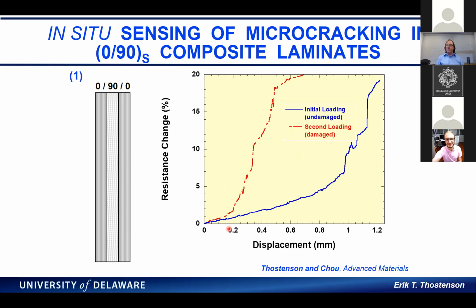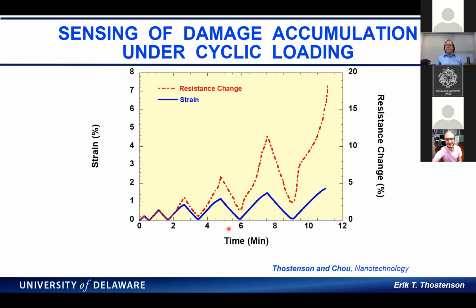So this was encouraging. So we did some more work where we were looking at if we loaded it in tension, those cracks would open. But then as we unloaded it, so that's the blue curve, that's the initial loading, those cracks would close on themselves. But when we reloaded it, those cracks would reopen at a much, much lower displacement. So the specimen was telling us, due to the piezo-resistive behavior and the opening and closing of cracks, something about the state of damage.